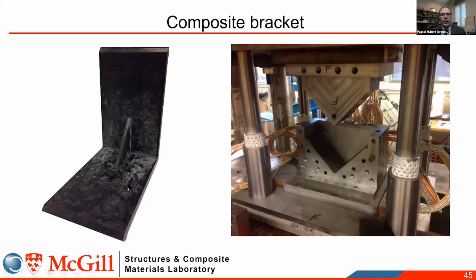It's just a simple bracket, but we have a feature here, a rib, that sometimes creates some problems in terms of the quality. Because when you make it in a mold that you see here, it's a cavity mold, so the rib will be on the top part of the mold here. And when you apply pressure, you might have problems maintaining that pressure during the process, and then you'll get some problems.